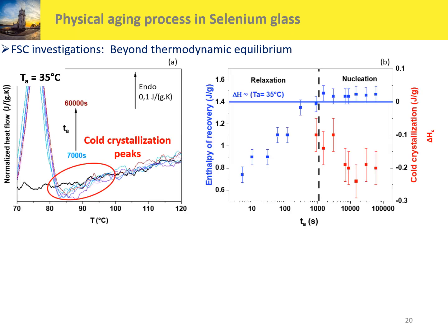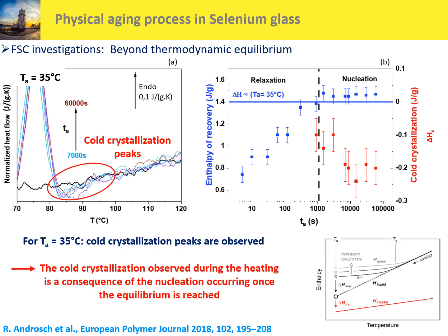So now, what about the physical aging process beyond the thermodynamic equilibrium? We perform new FSC investigations at aging temperature of 35 degrees C with different aging time. At a certain aging duration, we observe a cold crystallization peak during the heating scan after the aging. So for this temperature, we have a cold crystallization which appears, and this cold crystallization observed during the heating scan is in fact a consequence of the nucleation occurring once the equilibrium is reached after aging, as proposed by René Androsch et al.